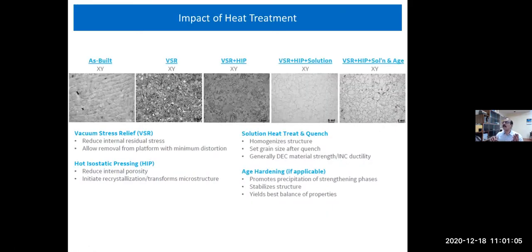And just look at the impact of heat treatment, which I was telling you about. This is the as-built property. Then this is vacuum heat treatment, vacuum stress relieving, the first one. You stress relieve in vacuum, you have a small refinement, then you go to HIP, the hot isostatic pressing, and you close up all the pores. Then you solution treat it, another heat treatment process, and then you age it, another heat treatment process. So you have this microstructure which gives you the best balance of properties.